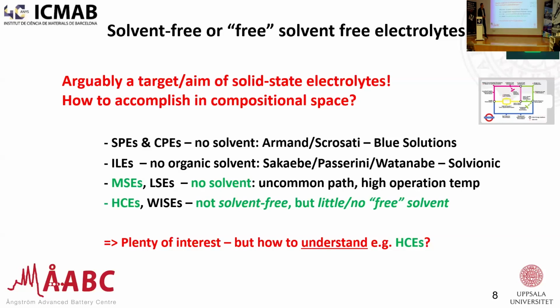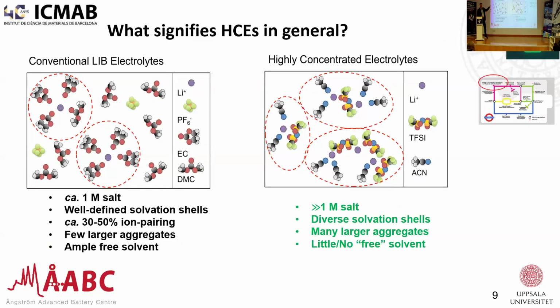So how do we understand this? Well, just highly concentrated electrolytes. Taking a traditional, conventional lithium-ion battery electrolyte, you have quite well-defined solvation shells. You have basically cations being dissolved in a solvent, and you can study it by any method, and you will see that it's very nicely organized signatures. Whatever you do, you have quite little cation and anion interaction. And this, of course, tells a lot about the performance that you get out in a battery eventually.